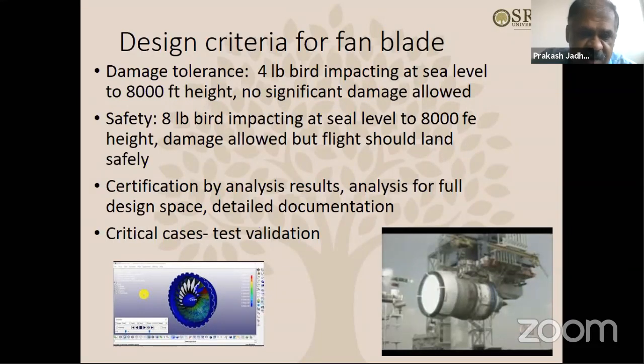certain blades you have to manufacture and take it to the test validation site. So the testing, as you can see on the right hand side figure, shows the test rig for the aircraft engine fan blades. As you can see, the engine is hanging there at the test site, and there are fan blades installed on the front side, and on the left side there's a gun. Okay, the gun shoots these gelatin birds, or real birds also sometimes. And as they shoot the bird, and the fan is rotating at 3000 RPM, it hits the fan blade, composite fan blade or metal fan blade, and then they evaluate the damage. Okay, this is the test site.